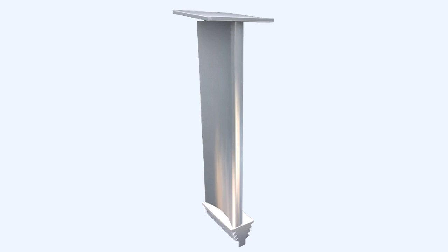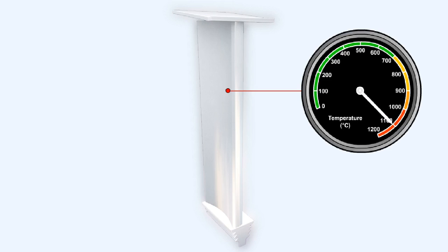Super-alloys are a complex mixture of many different metals: chromium, cobalt, nickel, titanium, tungsten, carbon, etc. Blades manufactured from super-alloys have a maximum temperature limit of approximately 1,100 degrees Celsius, or if the blades are cooled internally, 1,425 degrees Celsius.